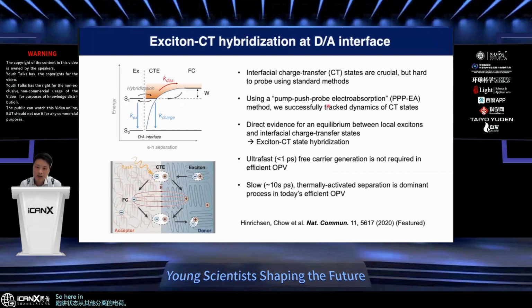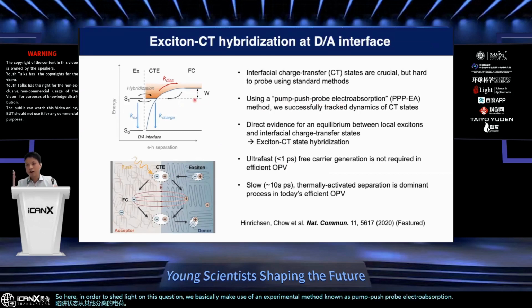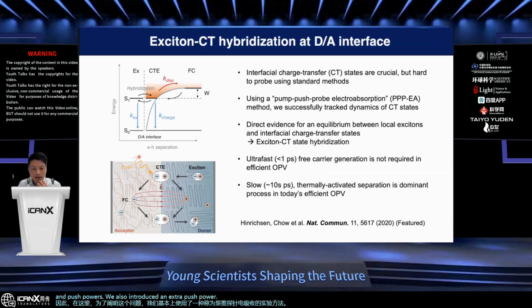charges. So in order to shed light on this question, we made use of an experimental method known as pump push probe electroabsorption. Besides the pump and the push pulse, we also introduced an extra push pulse that is only sensitive to the CT states. This is obviously quite a complex experiment, but we did a lot of control experiments to make sure that the push does not affect the free charges, and it doesn't affect the excitons. So it would only interact with the trapped CT states buried at the interface. Using this method, we were able to get direct evidence that these states do exist.